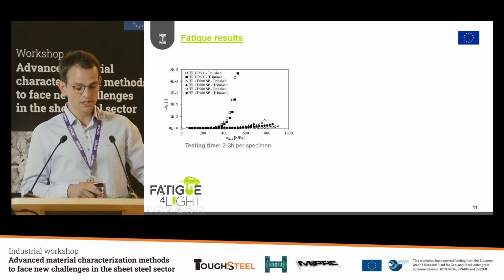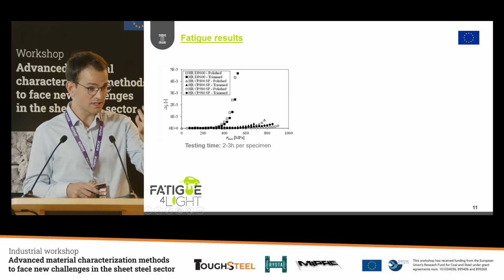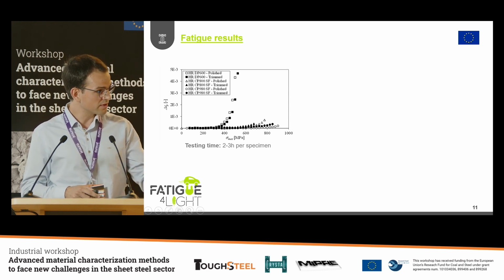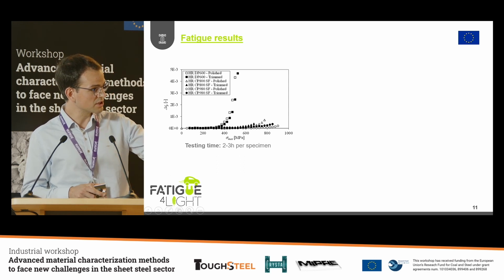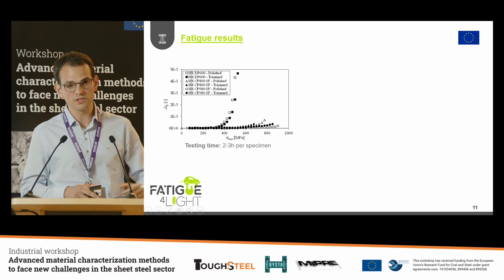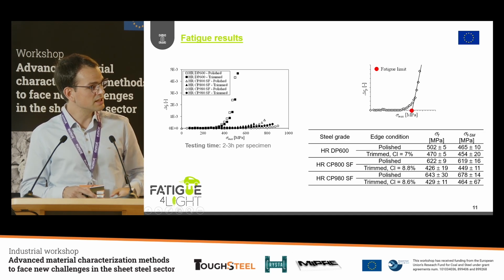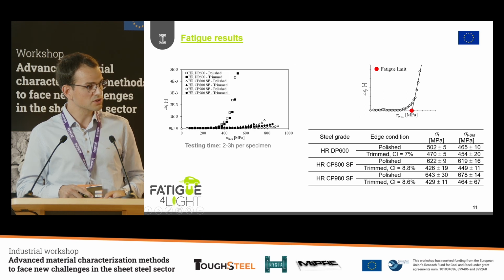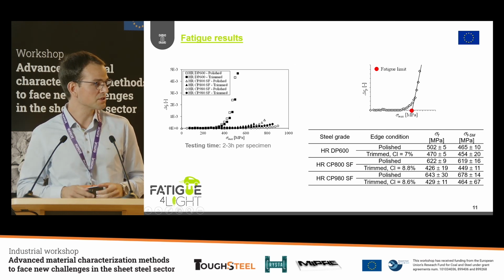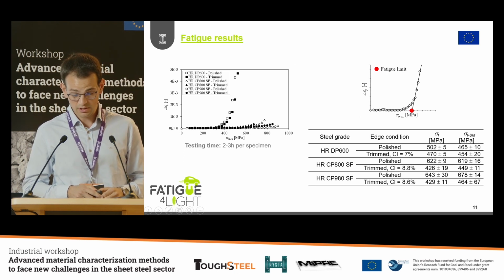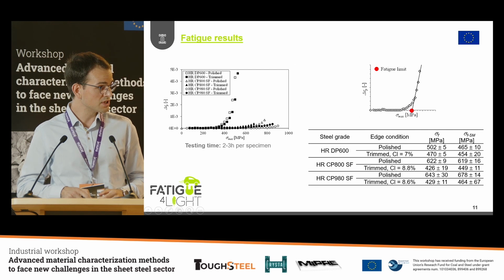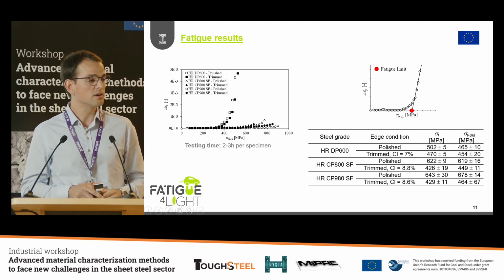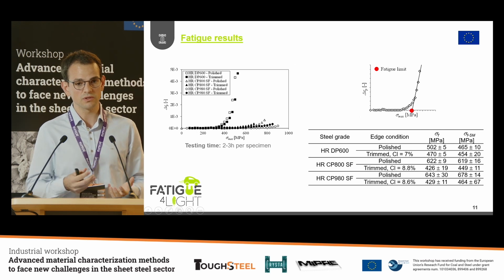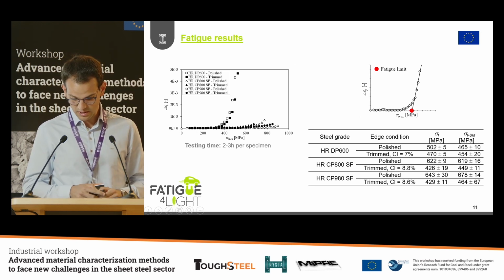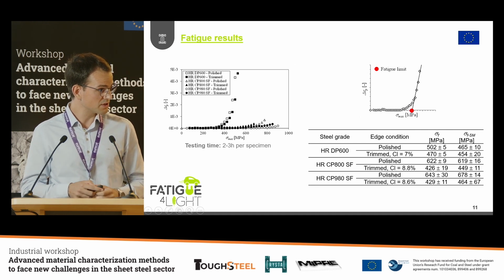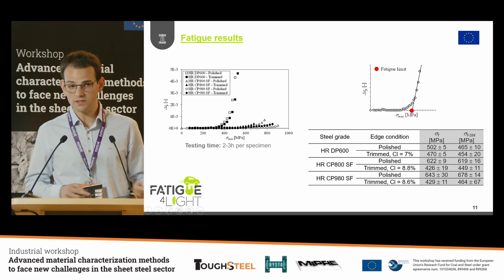In this case, you can see the plastic strain. So this is the damage, let's say, that we have in the material and how it's evolving throughout the test. So it is the plastic strain plotted against the maximum stress amplitude for each fatigue block. And here, by analyzing this data and using the points that belong to microcrack initiation and also microcrack propagation, we can easily determine the fatigue limit of the material with the different conditions. And also here we compared the results from the rapid fatigue method with the results obtained by the staircase method, so the conventional methods, and we obtained, let's say, the same results.